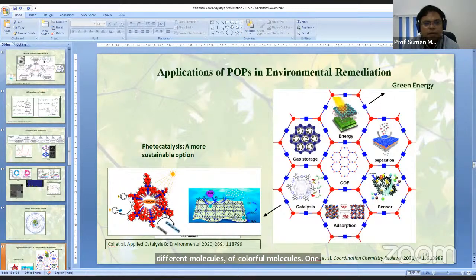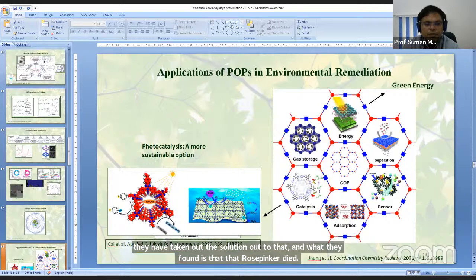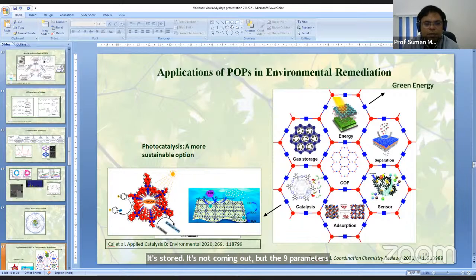One is rose Bengal dye, which is a pollutant, and they have taken a marker nitroaromatic, I think nitrotoluene, and added it in. They pass this mixture of solution through this membrane and take the solution out. What they found is that the rose Bengal dye gets totally adsorbed, it is not coming out, but only the nitroaromatic, that is the nitrotoluene, is coming out.